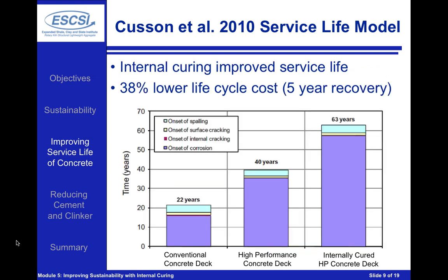Now, one of the main takeaways from this study can be seen in this bar chart. If we look at the comparison of conventional concrete to high-performance concretes, we can again see the same type of benefit that we saw when we compared the Monroe County bridge deck to the bridge decks from New York, where we can see that the service life would move from approximately 22 years to approximately 40 years for going from a conventional to a high-performance concrete.